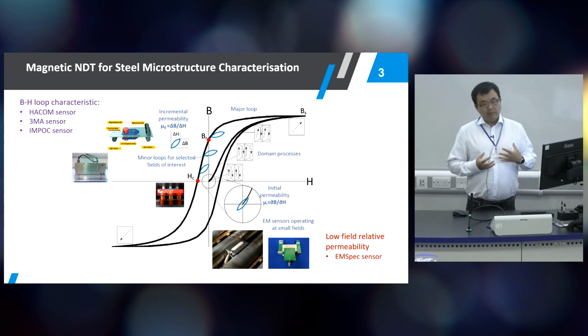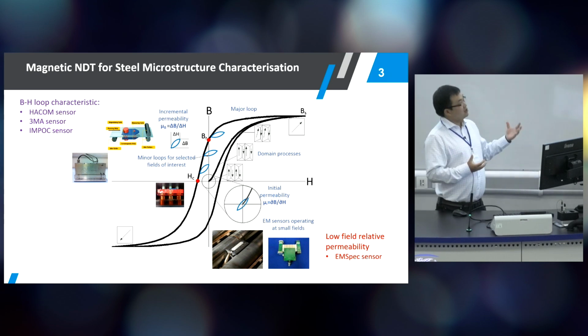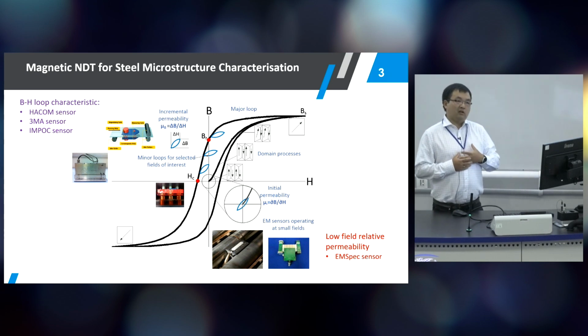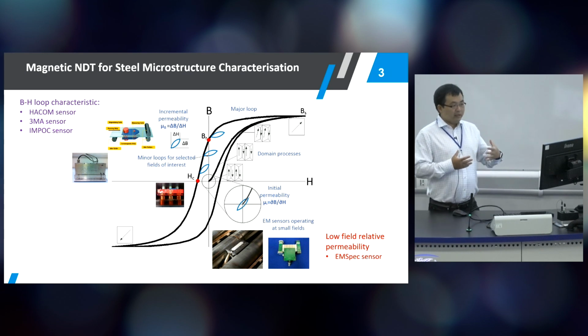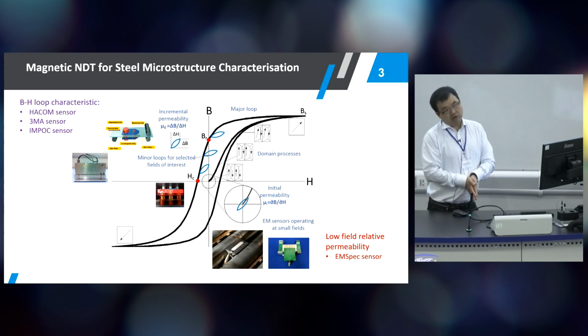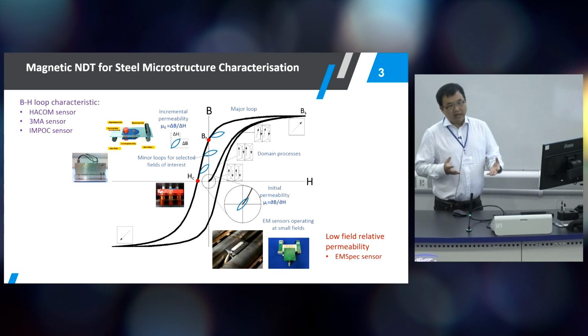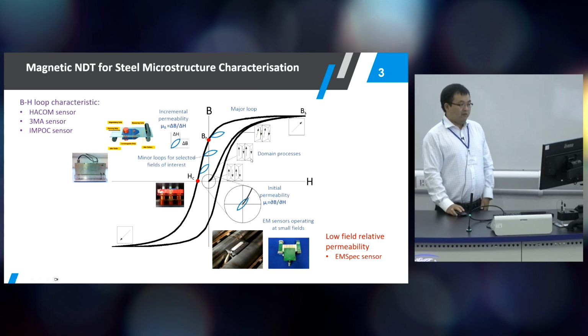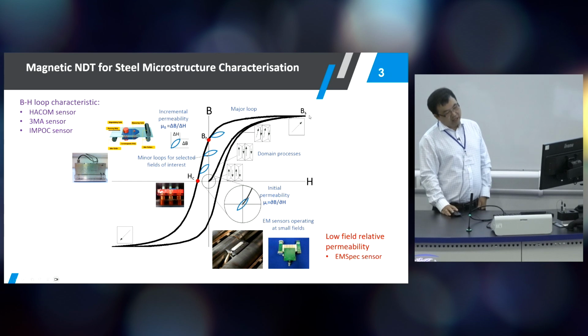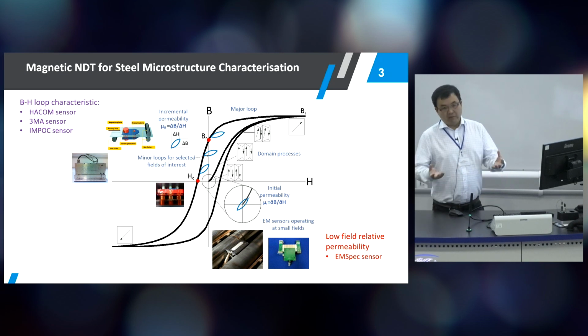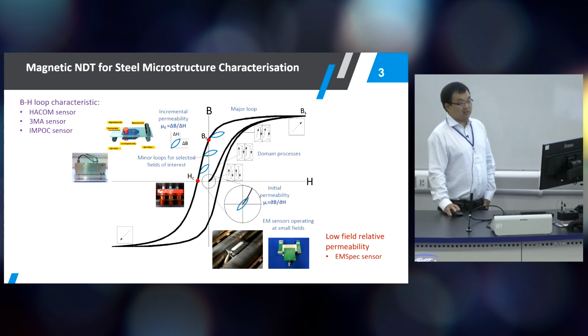So what happens is when you apply an external magnetic field, the domain structure starts to move and the domains start to align with the external magnetic field. And of course, when the domain wall is moving for the domain alignment, the domain wall can interact with microstructure features. And this is why the microstructure and magnetic properties are linked to each other. So if we magnetize the sample fully at a very high field, achieve saturation, and then we relieve the magnetic field, the steel actually comes back at a different point. Sometimes we have a piece of steel that is close to a magnet for a long time, and then you have some remaining magnetism there, and we call that the remanence point.